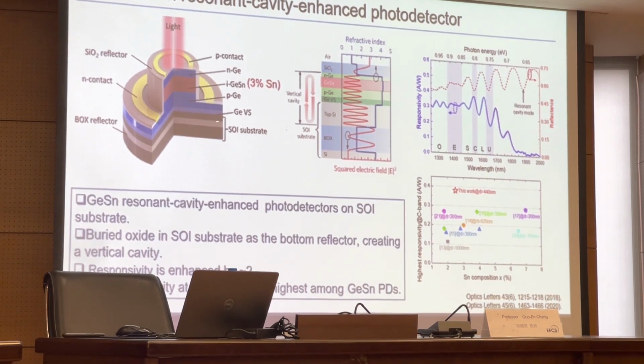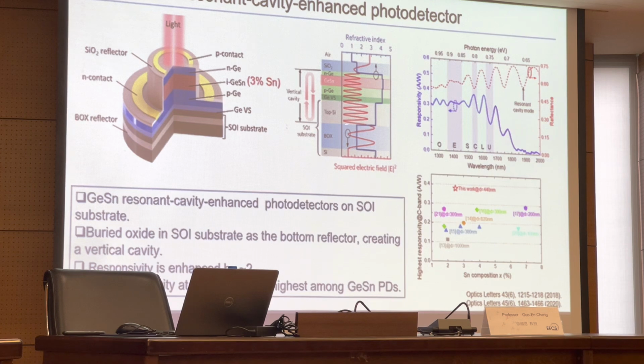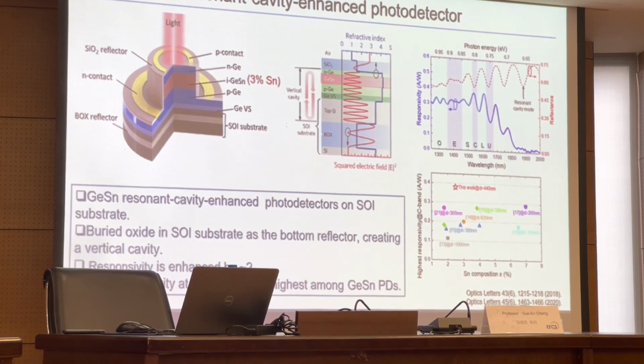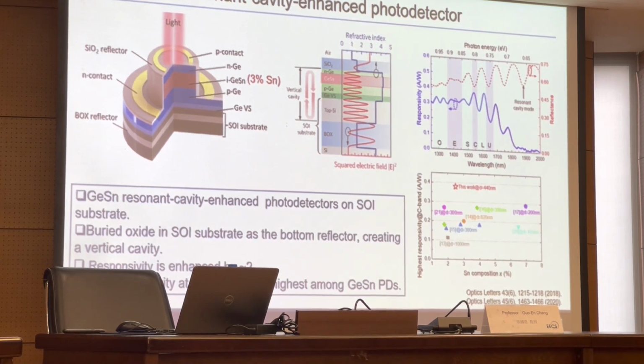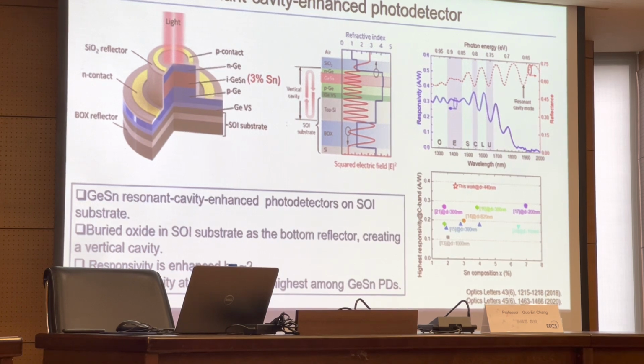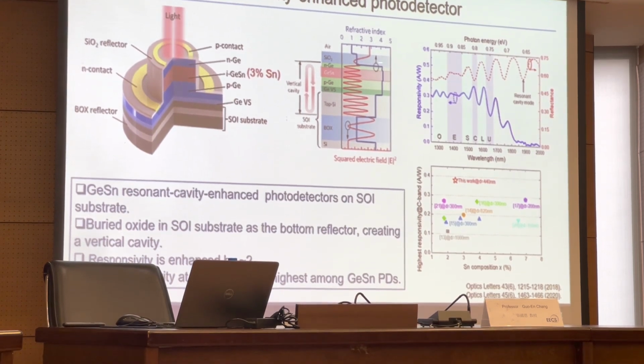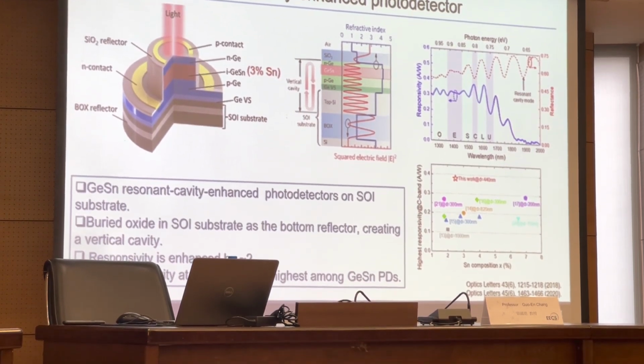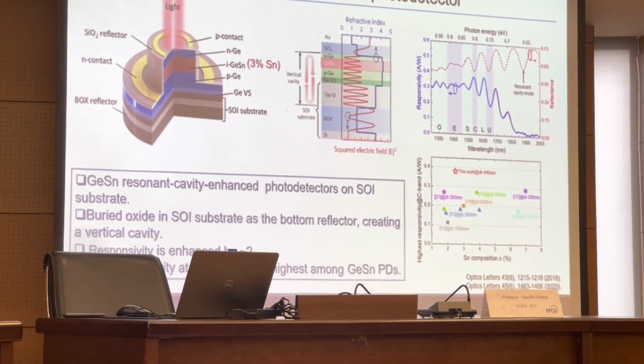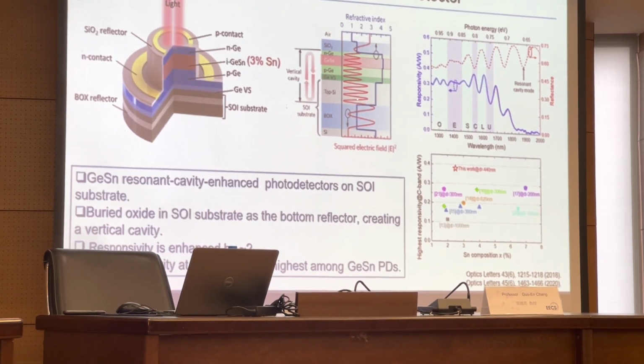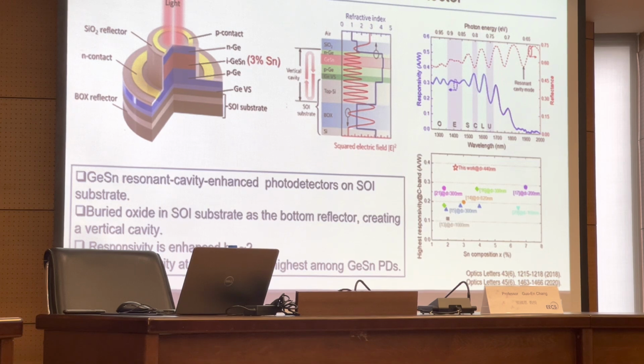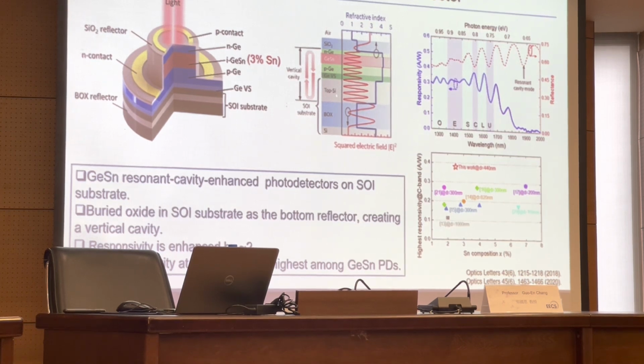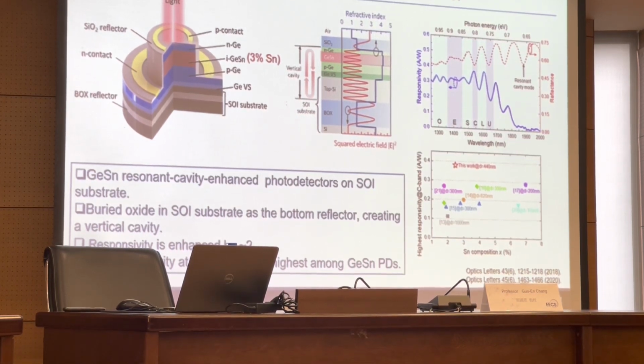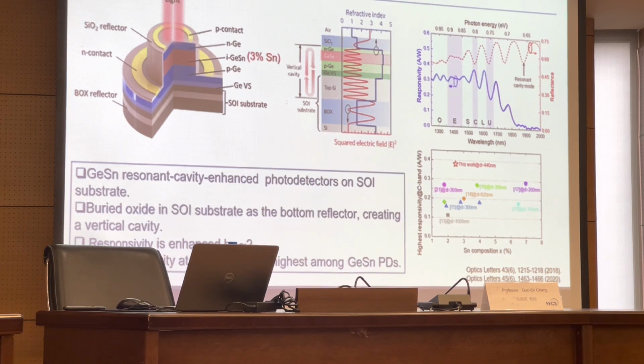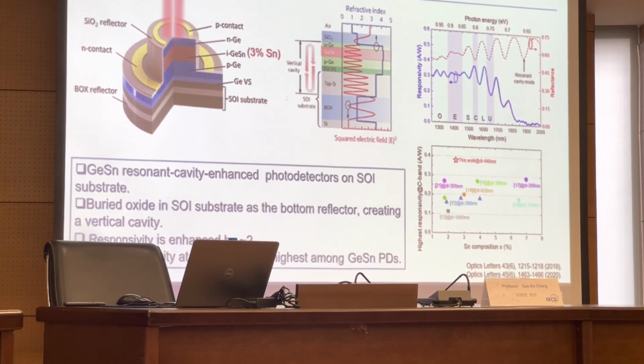The buried oxide layer has a very low refractive index, about 1.45, while semiconductors have a refractive index around 4. So if we grow germanium layers on an SOI substrate, we naturally form a vertical cavity, then we fabricate a normal incidence photodetector.